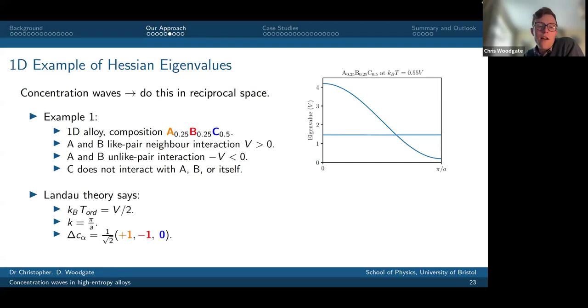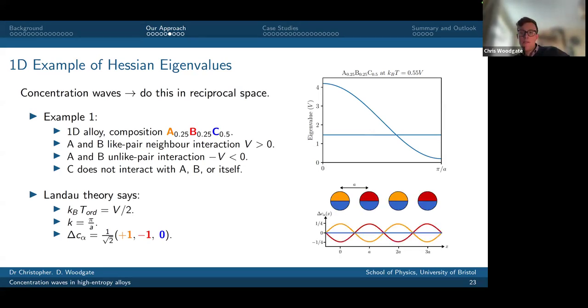And if I work through the Landau theory, I find that my ordering temperature, k_B T_ord, is equal to V over 2. Okay. And I describe the situation exactly as I had on the left in that previous slide, where I want to get alternating AB ordering with C remaining disordered. Okay, so that's very nice. And so this Landau type theory gives me an estimate of the ordering temperature and allows me to infer the nature of the ordering. Okay.